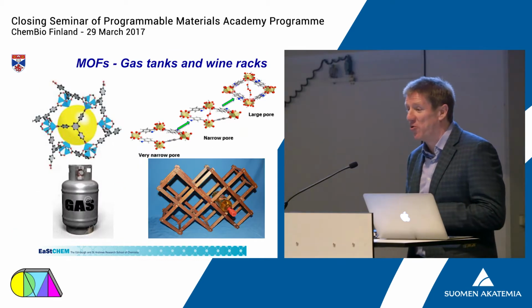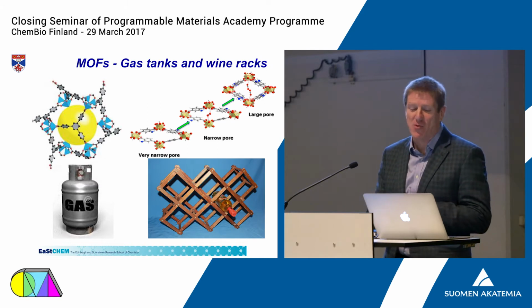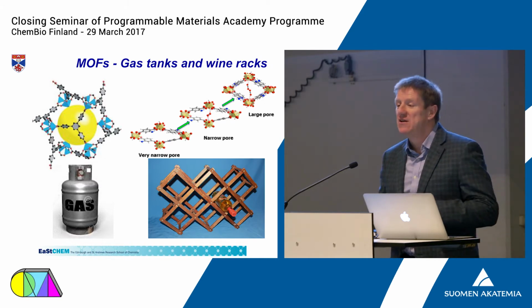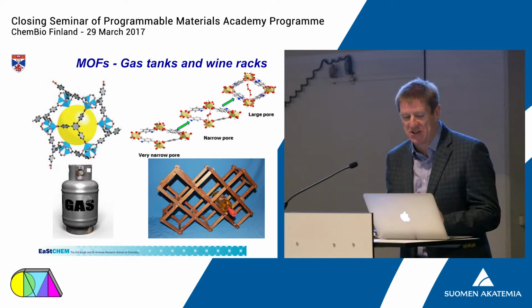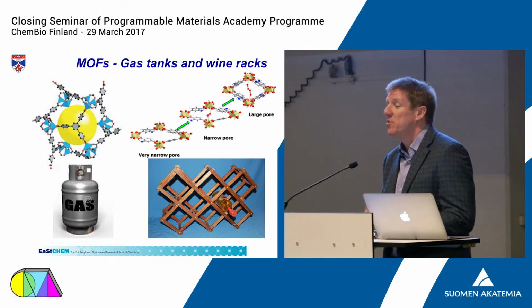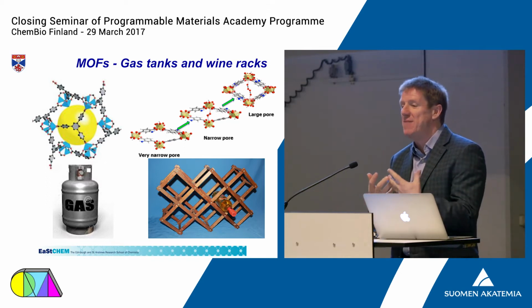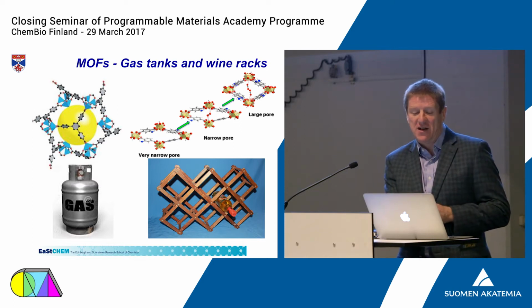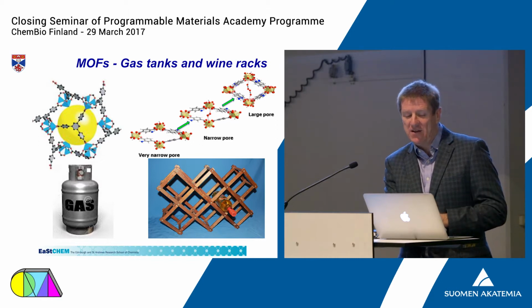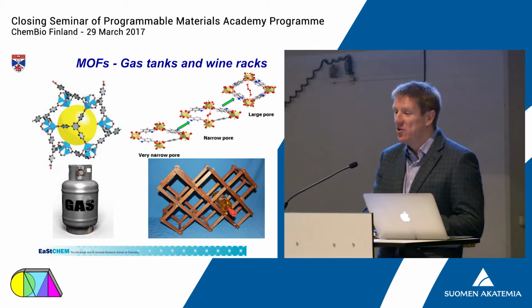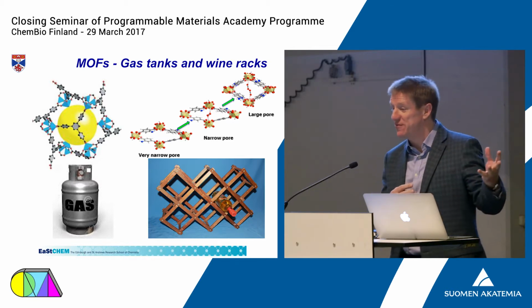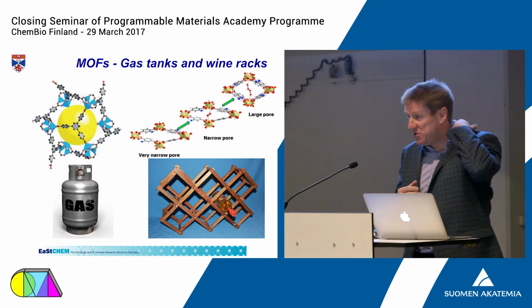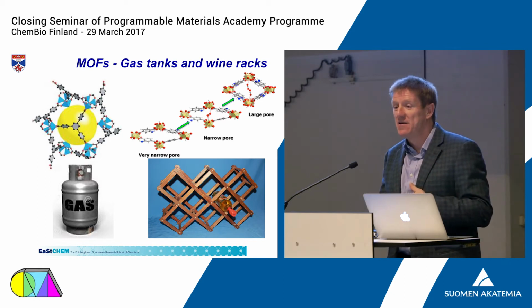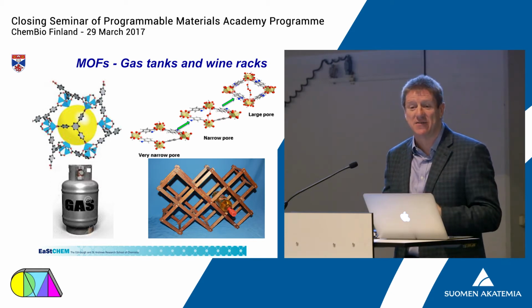There's a different type of porous material called a metal organic framework, a MOF, which has similar porous properties, but completely different chemistry. They're metals in the corners, linked by usually fairly inflexible organic groups to leave lots of space, which in the best situation you can remove the stuff from inside there and leave highly porous materials. And they make particularly good gas tanks.